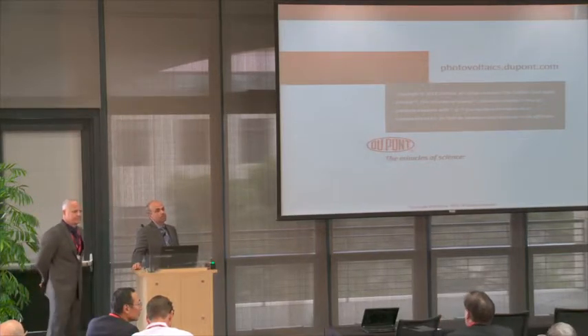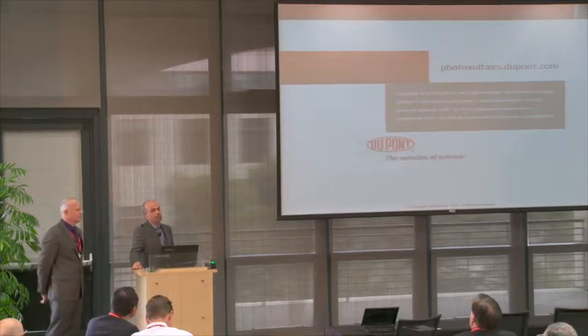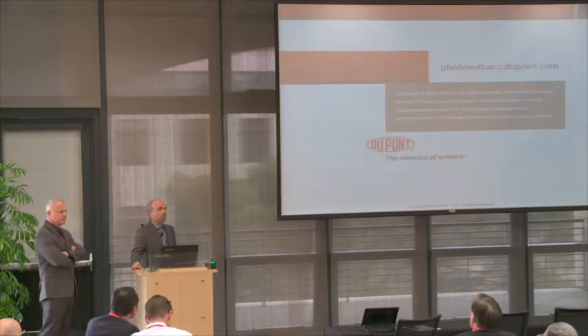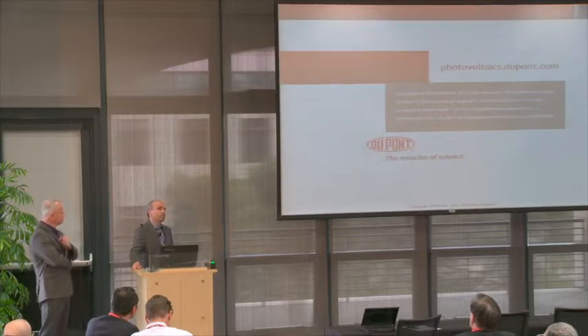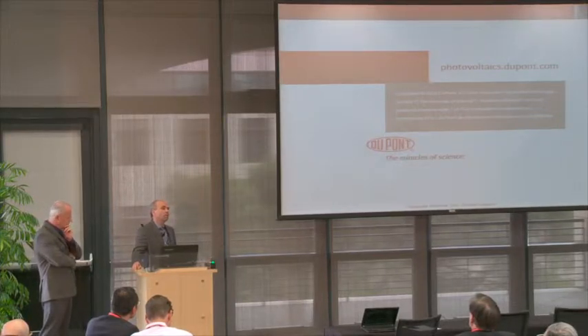What is desirable is to have about 0.5% loss per year for the crystalline silicon panels. And of course, at the end of life, 25 years or so, you don't want to be below 80% of the maximum. So even after 25 years, the panel will continue to operate. Now, of course, the lifetime is extremely important because it's directly linked to your investment. The slower the degradation, the higher the return on your investment. So you want to be aiming at better than or equal to 0.5% annually, not more.